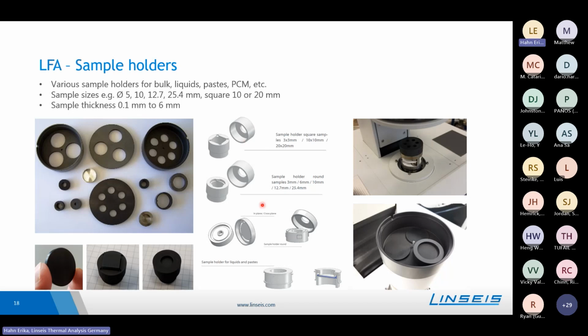But we also have some special sample holders. So, for example, one for pastes, powders, and liquids, or for some in-plane measurements. The sample preparation is quite simple, so one needs to prepare the sample according to the size of the sample holder. We then cover both of the sides with some graphite spray. This is done to maximize the absorption and emission of the sample.